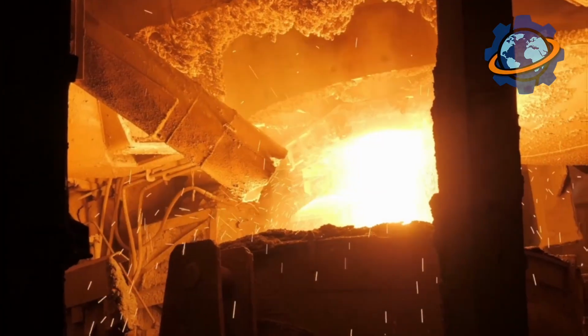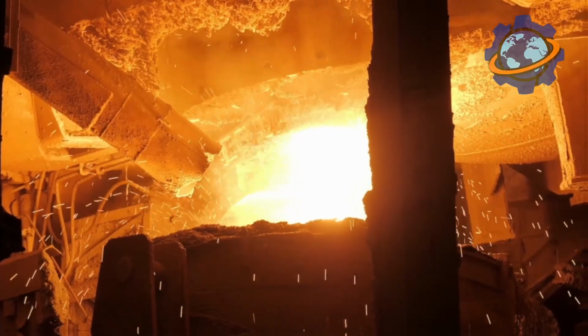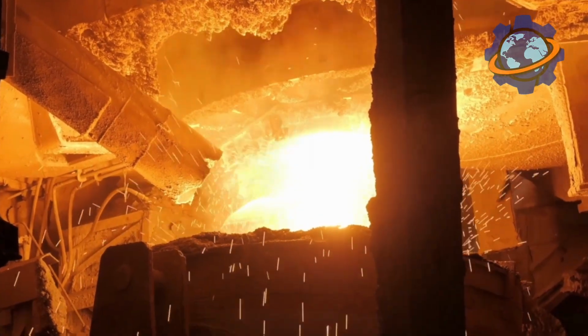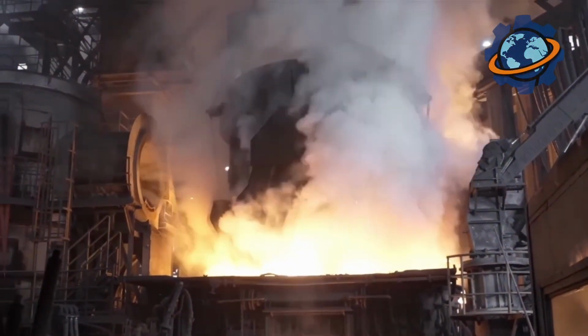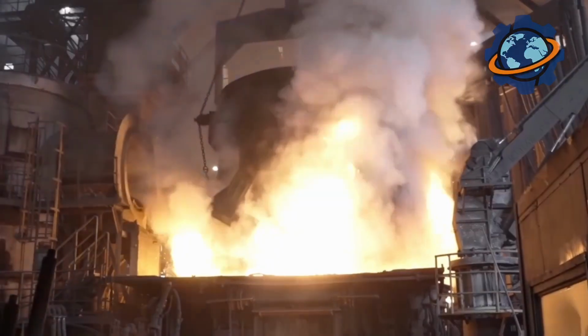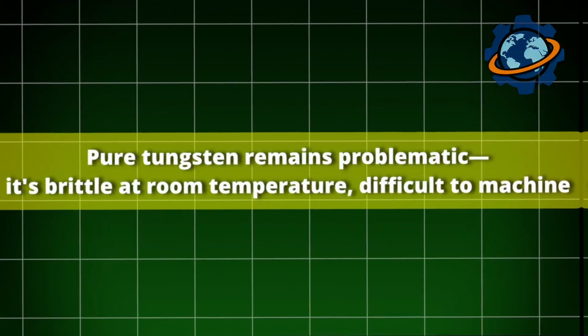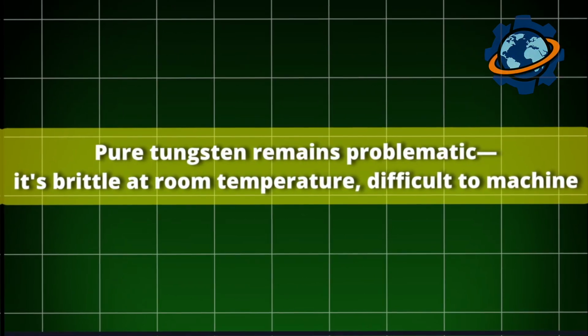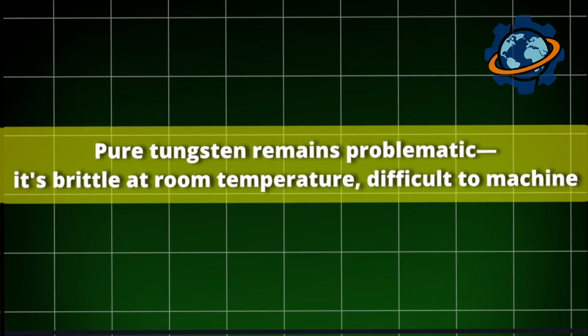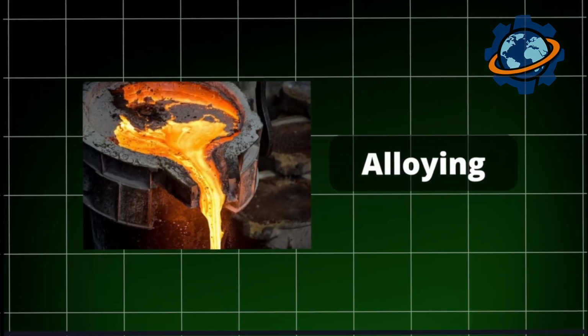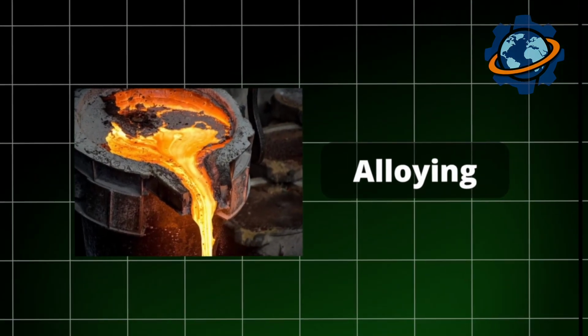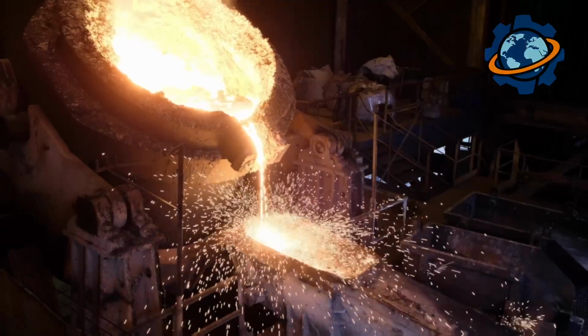Dimensional changes are predictable but significant. Parts shrink 18% during sintering. Engineers must design oversized greens compensating for this shrinkage. Pure tungsten remains problematic. It's brittle at room temperature, difficult to machine. The solution? Alloying. Adding 2% thorium or lanthanum dramatically improves workability.